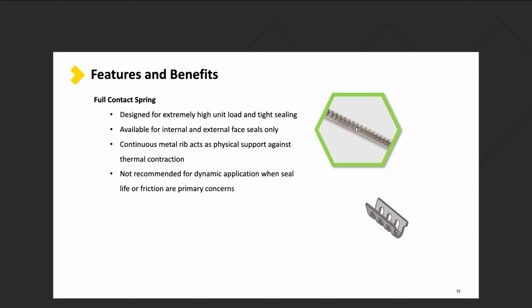The advantage then of the full contact spring is that it's a mechanical support as well as a spring energizer. When we get into extreme cryogenic applications, minus 300 degrees F and lower, the Teflon jacket has a coefficient of thermal expansion 10 times that of the metal that surrounds it. So that seal wants to pull away from the hardware. The advantage of this spring, it has that mechanical support in that it'll keep the seal in place in those extreme cryogenic environments. Fantastic for that.